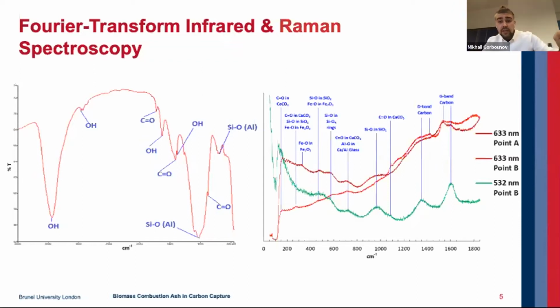So the two outermost left peaks on the FTIR, on the left there, have been attributed to the stretching and the bending vibrations of the OH bond respectively. And this functional group is visible on the spectrum due to one of two reasons. The first one being that it occurs naturally and is present within the hydroxides, or it could be there due to the physisorption of water by the surface. Apart from that, both symmetric and asymmetric stretching, as well as bending vibrations for the carbonyl group COO have been identified. The same as with OH, they could be attributed to the carbonates present or to the CO2 physically absorbed, but we prefer to stick with the first option for both of them.